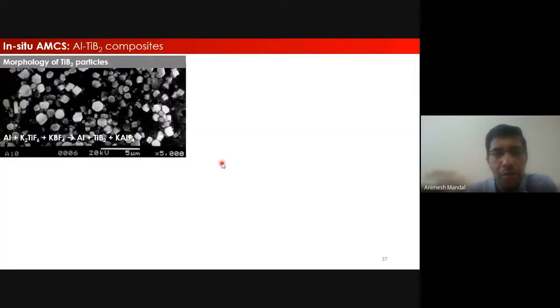The other class of composites we can call the in situ composites. In this case, you do not add the particles from outside directly. Rather, you add certain raw materials which will react within the melt. As a result, they will form the reinforcements. For example, let us take the case of the aluminum titanium diboride composite. Here you can see these are two fluoride salts of potassium, one is the titanium salt, one is the boron salt. If you mix them in a particular ratio and add them to molten aluminum, they can react and form titanium diboride particles. You can see these beautiful hexagonal particles of titanium diboride.